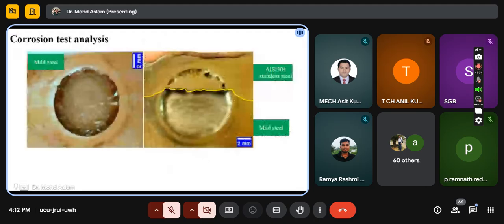And after that, you can easily see the corrosion test analysis sample here. In the case of mild steel, 100% of the part was corroded. At the cladding interface, in the second sample, we cladded mild steel to stainless steel. Mild steel is a 100% corroded material, but the stainless steel has less material corroded. And here at the corner, some parts corroded more, due to the high current density passing through the contact area, compared to other steel parts.